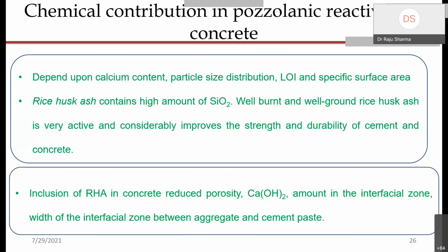Therefore, this improvement in well burnt and well ground rice husk ash can give you products like ultra high performance concrete also. So many publications in the field of ultra high performance concrete are developed with rice husk ash. So inclusion of RHA in concrete reduces porosity and reduces the amount of calcium hydroxide in the interfacial zone, the width of the interfacial zone between aggregate and cement paste. So ITZ is a very important part because it's weak.